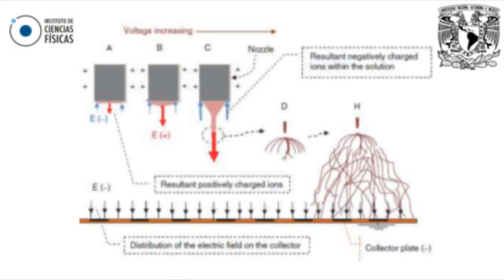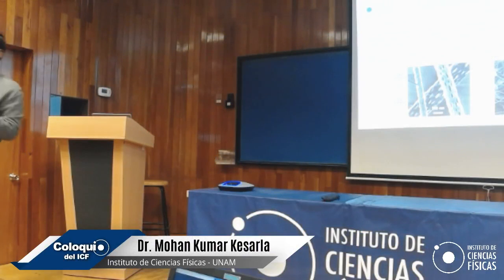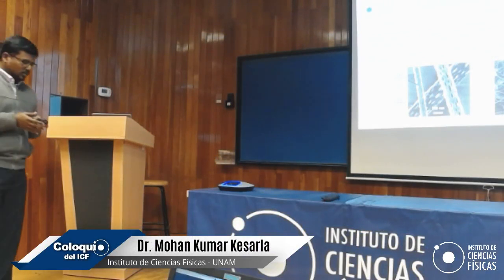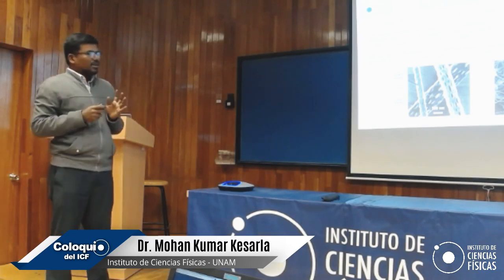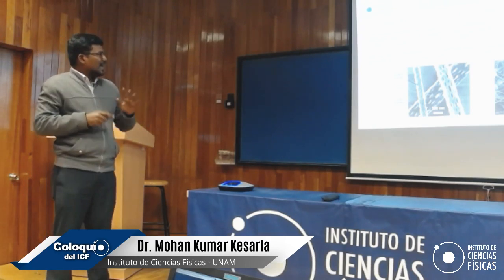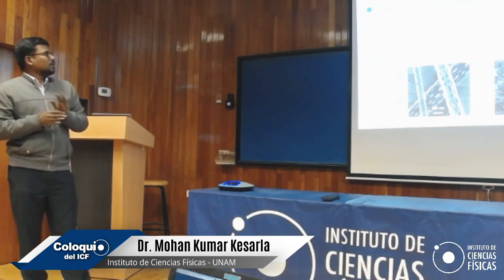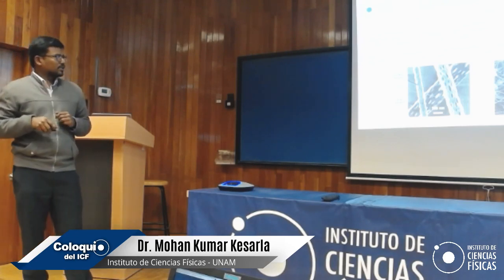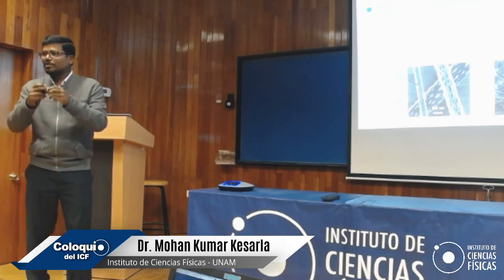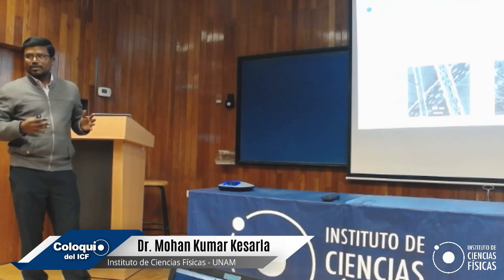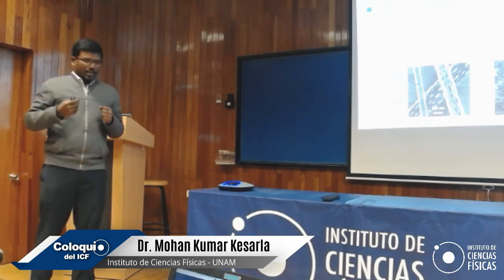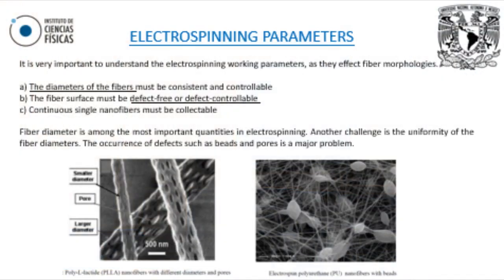But it is not as easy as I am making it sound to form nanofibers. There are various parameters you have to take care of in order to get a particular nanofiber. As far as nanofibers are concerned, controlling the diameter, getting defect-free fibers, and collecting uniform fibers is very, very difficult. If you look at these two pictures, instead of getting fibers, I am getting fibers with spindles. And here, instead of getting a fine fiber, I got a porous fiber. So each and every parameter is very, very important.